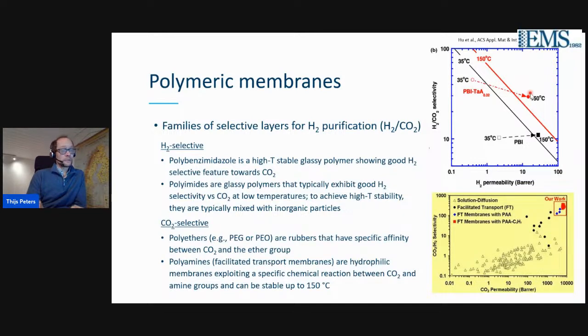The reverse selective membranes, the CO2 over hydrogen selective, then again need to be facilitated transport. They can be made out of polyethers. The PEG or PEO are rubbery polymers with a specific affinity between CO2 and the ether group. And the polyamines are again the facilitated transport membranes that need to operate under high humidity. These are hydrophilic membranes exploiting again the specific reaction between CO2 and the amine groups. And these, under some conditions, can be stable up to 150 degrees.